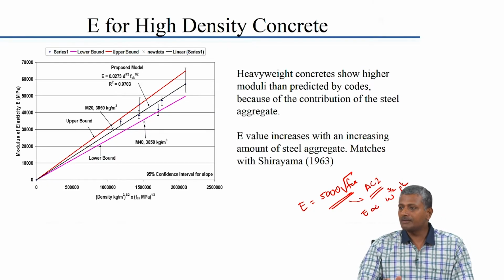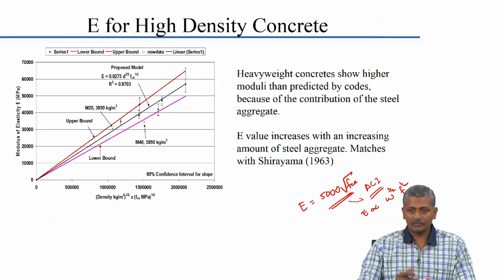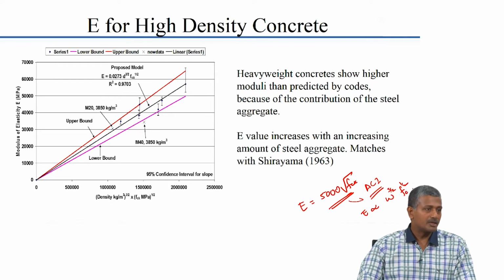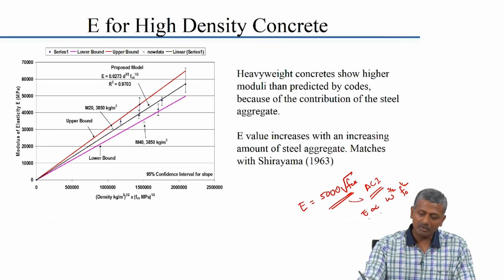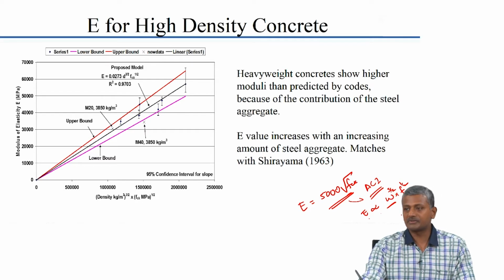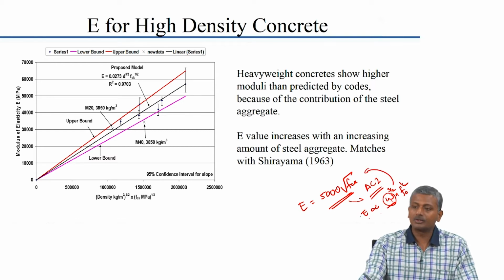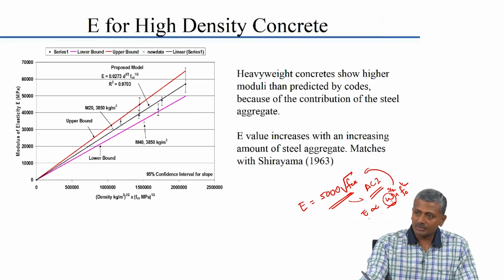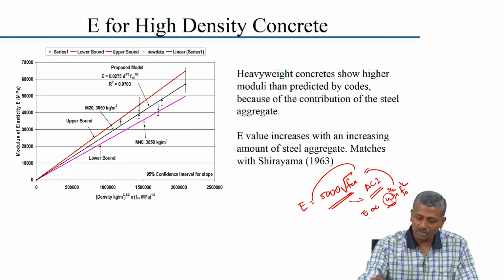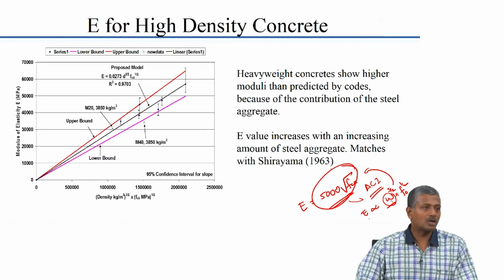Originally, when this relationship was first proposed, it was based on the fact that the modulus was seen to vary directly with the 3 by 2 power of the density multiplied by the square root of the compressive strength. For normal density concretes, when you convert this density into a normal value like 2400 kilogram per cubic meter, this entire expression translates into 5000 square root of fck. For high density concrete, we found that this relationship was really not predicting the moduli of elasticity well enough.